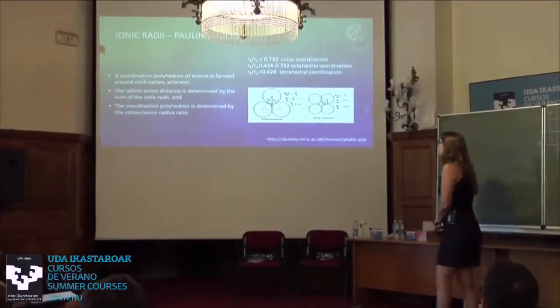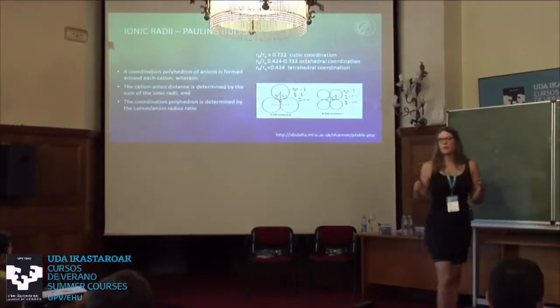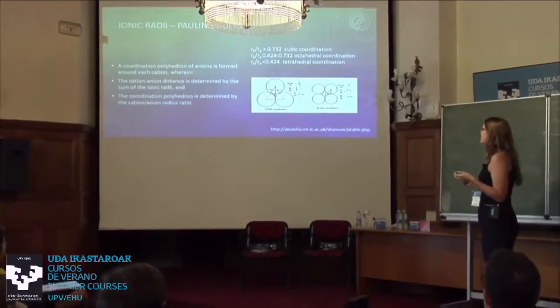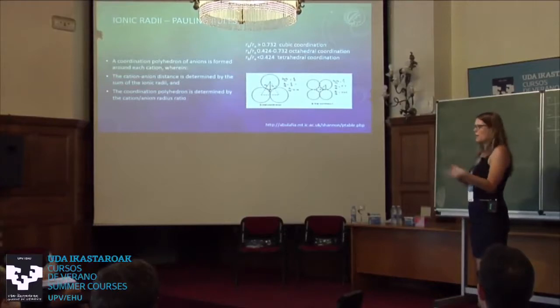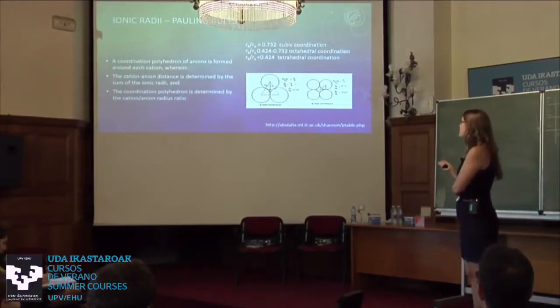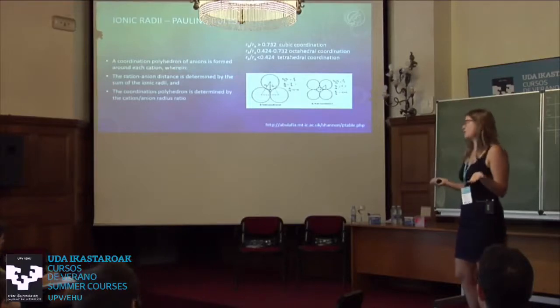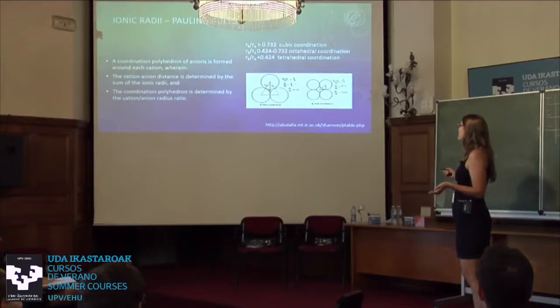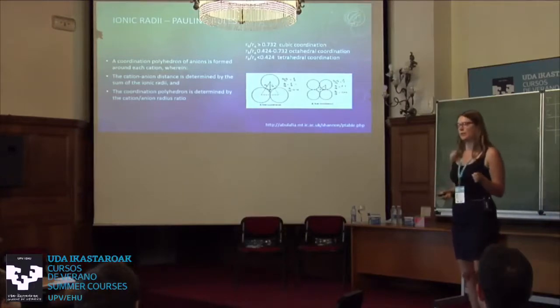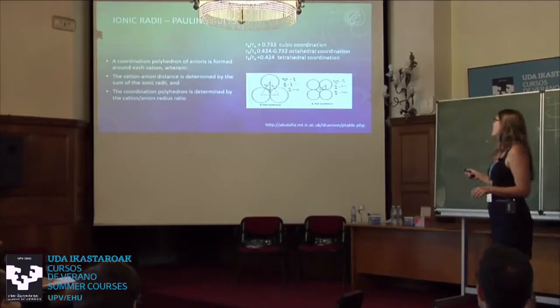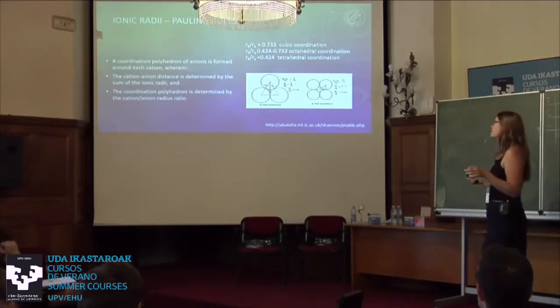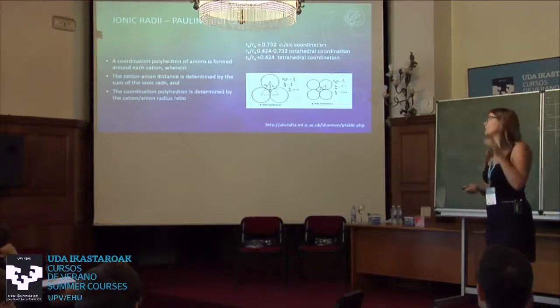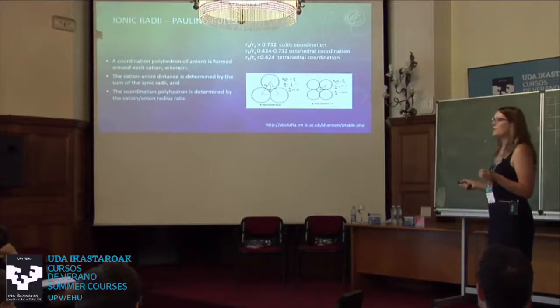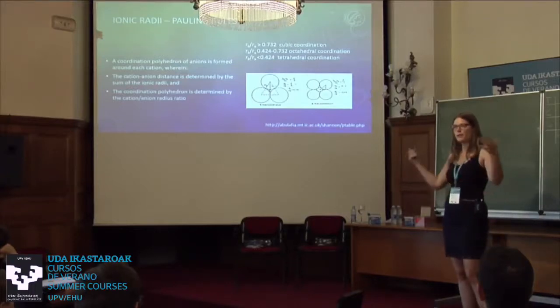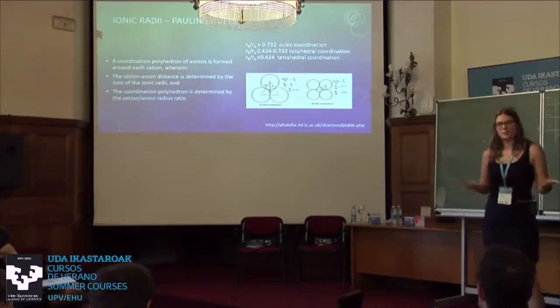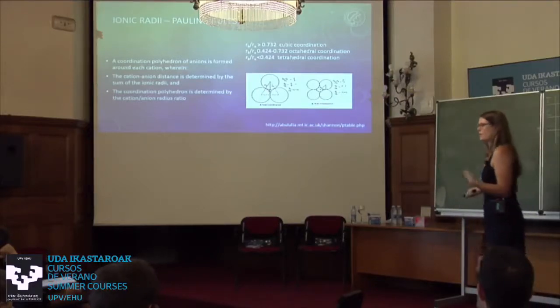And for example, for oxides, there are some really nice rules you can follow to have an idea what the sizes do, because in oxide chemistry, or even other really ionic compounds, you can take the ratio of your cation and your anion, which would be oxygen, and depending on the ratio, you can get the coordination number. So if you have a large ratio, you will have a cubic coordination of your cations. With an intermediate one, you can have an octahedral coordination. And with really small ratios, you can have a tetrahedral coordination. And so if you want to make up a new compound based on this, you have to make sure that it fits those rules. Okay, and we'll come back to this later of how it doesn't work in some cases.